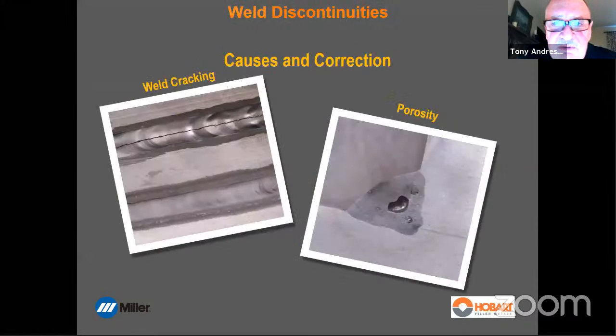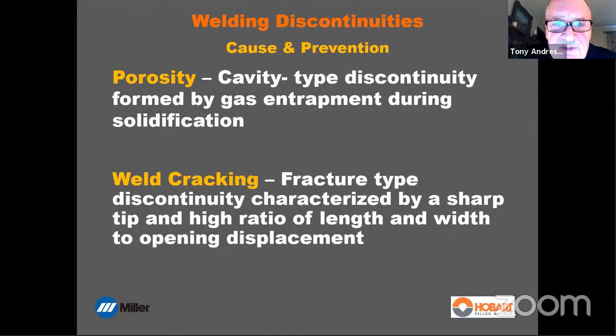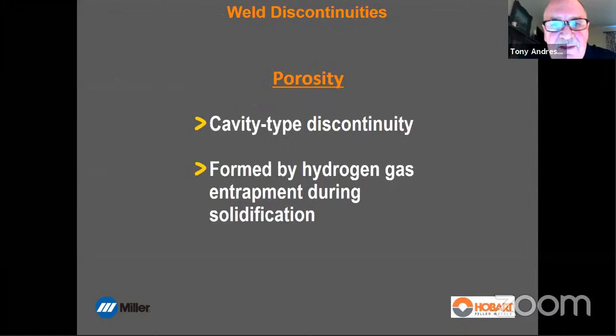All right, so we're going to talk about weld cracking and porosity. So porosity. Cavity type discontinuity, we all know what porosity is, right? It's caused by gas entrapment during solidification. And cracking, fracture type discontinuity, and that's the AWS definition, the height to depth ratio and so on. So we all know what a weld crack is. Moving on from there. Porosity, again, cavity type discontinuity, and it's formed by hydrogen gas. This is really important, and which is entrapped during solidification. It's all about hydrogen in aluminum.